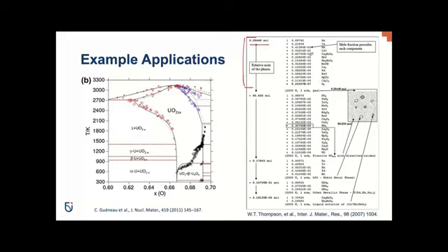Xenon is predicted to be the most dominant in this case, not surprising at all. Then followed by the fluorite UO2 solid solution phase with various dissolved fission products. And you can see here the total quantity of the fluorite phase, in addition to various species that are predicted within it. UO2 is the most dominant in this case, followed by plutonium and various other fission product species. Noble metals follow. This is commonly referred to as the white phase with the hexagonal close packed crystal structure and so forth.